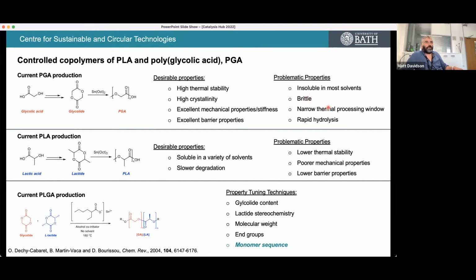It's brittle, it's very difficult to process, but perhaps most importantly, it hydrolyzes very rapidly. So it's a difficult polymer to ship around the world and do post-polymerization processing on. You can see why, because there's no steric hindrance of the methyl group of the PLA here. However, it does have very high thermal stability. It's highly crystalline, again, because there's not that steric hindrance there, so you get really good monomer interactions.